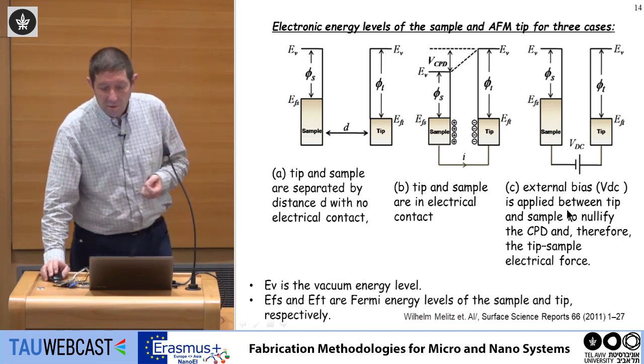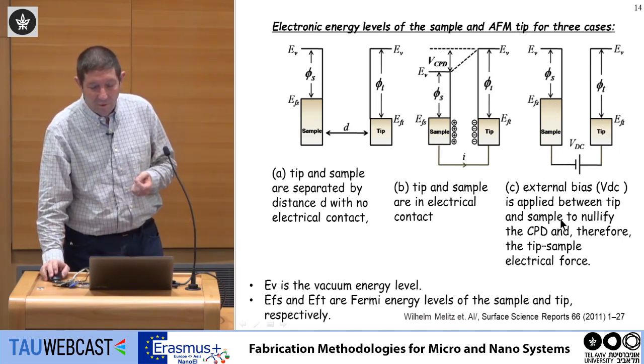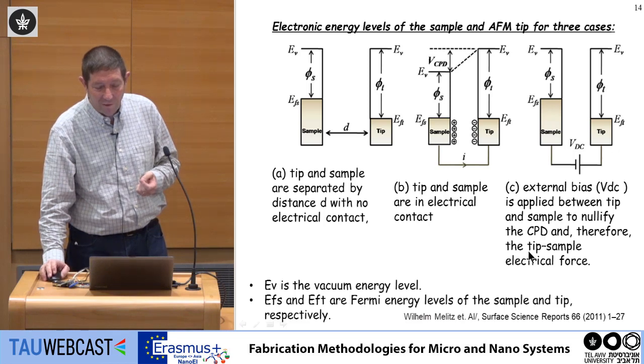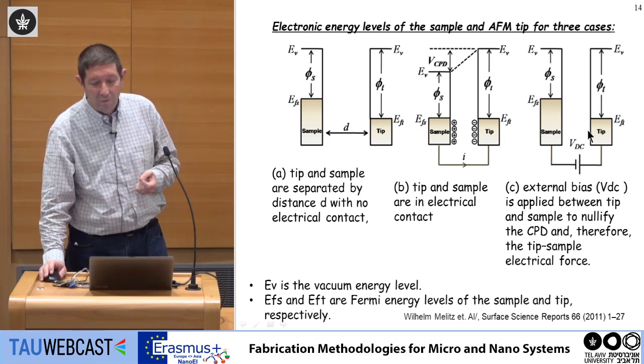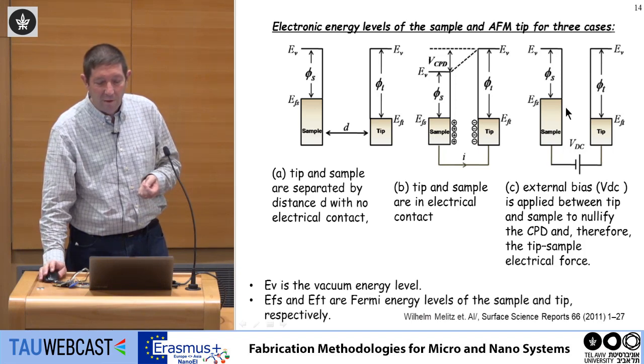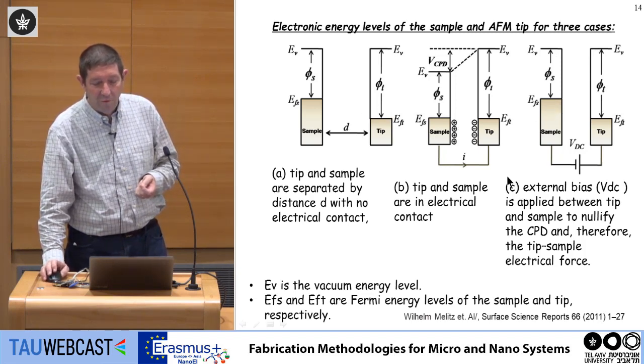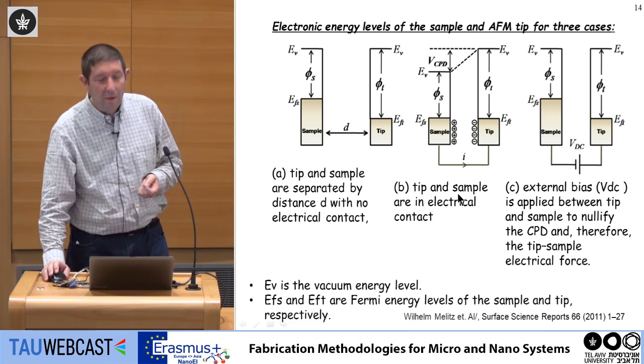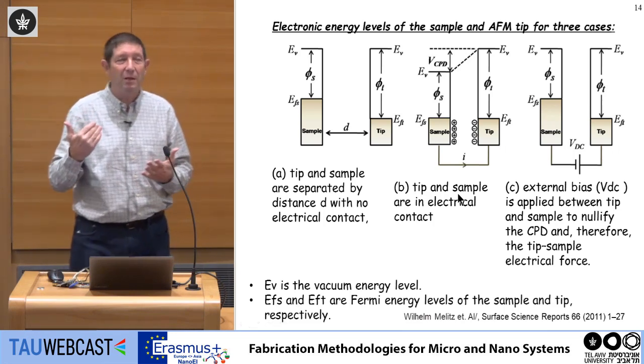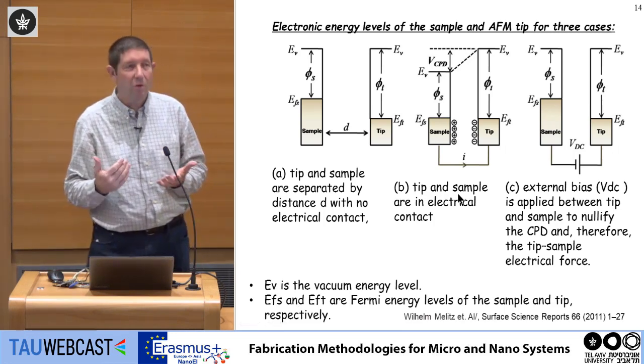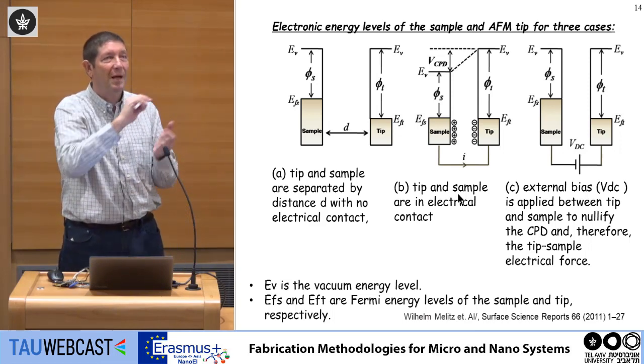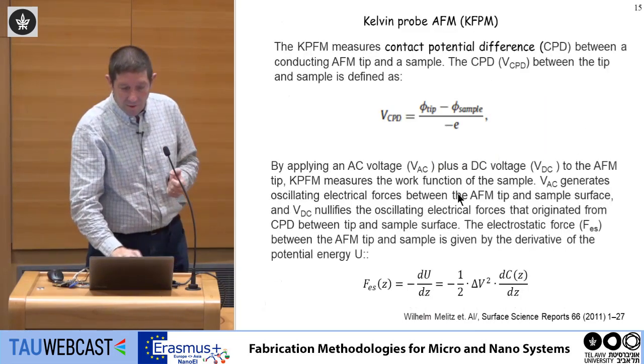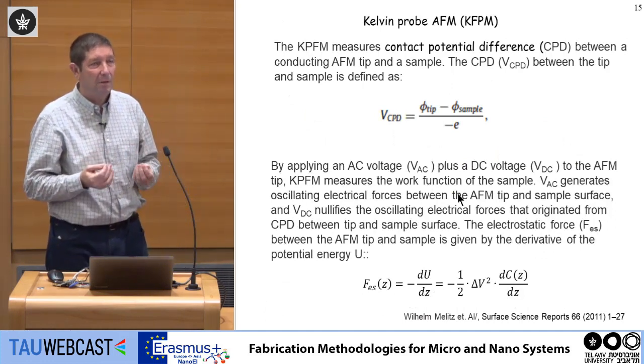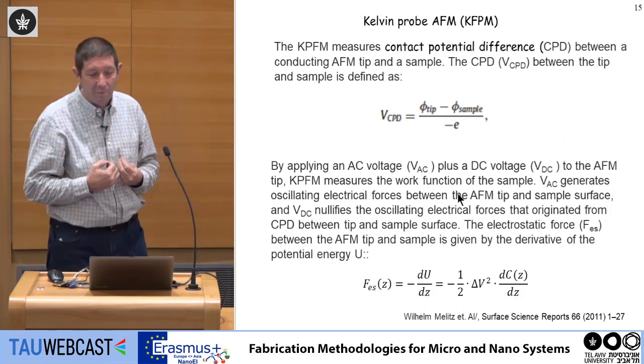So an external bias VDC is applied between tip and sample to nullify the CPD and therefore the tip-sample electrical force. By applying a voltage, I can, for example, nullify the potential difference, and I can use this effect. In the previous AFM system that I showed you, I just measured the force, but I can apply a bias between them. And this is the key to another tool, which is called Kelvin probe AFM.